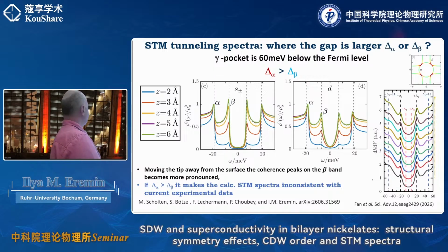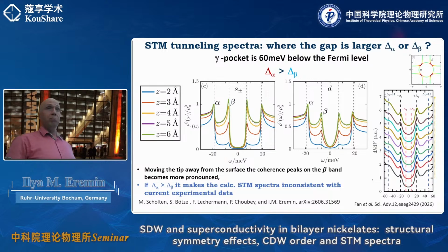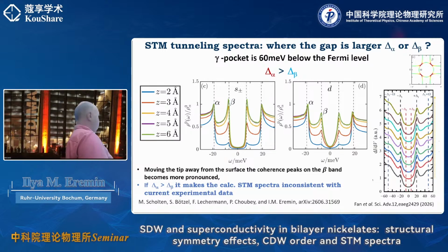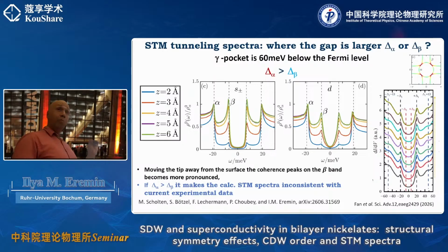But the moment that the tip moves away, you start to see that the coherence peak on a beta pocket, which has a smaller gap, would start to increase and start to be completely incompatible with experiment. This is clear why, because the beta pocket has a lot of z-square contribution, much more than the alpha pocket. So this basically leads you to conclude that although it's hard to distinguish between S plus minus or D wave, what you can certainly say is that it cannot be the case that the largest gap is sitting on the alpha pocket. So it must be on the beta pocket.